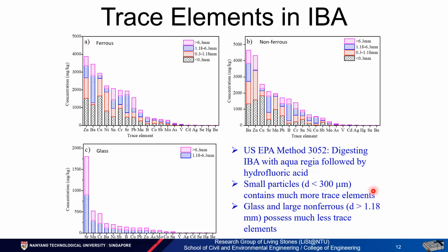In contrast, the glass and the large non-ferrous particles are much cleaner, showing much less trace elements. So that's an indication about the concern of heavy metals.